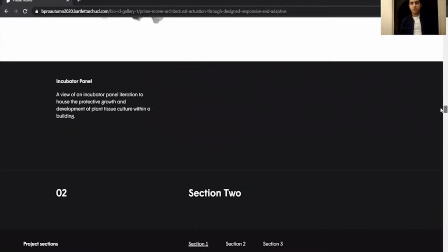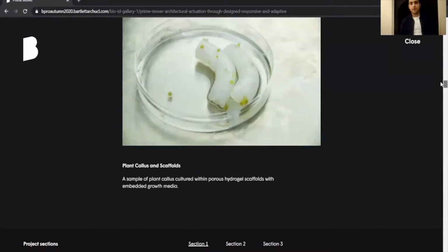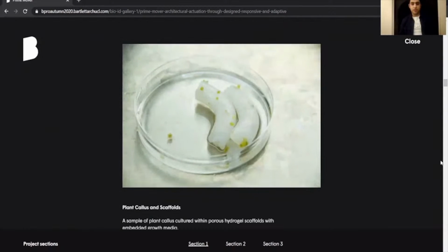The common feature in all biopolymers with high water ratio is that they lack the proper structural integrity for being three-dimensionalized. Therefore, it was compulsory to adjust the ingredients to achieve a configuration with the necessary structural stability. But considering all adjustments, fabrication with normal robotic extrusion methods will result in collapse of the geometry after adding more than a few layers upon each other, due to the material's relatively low compressive strength. So we had to base our fabrication process on exploiting the higher tensile strength in our material.